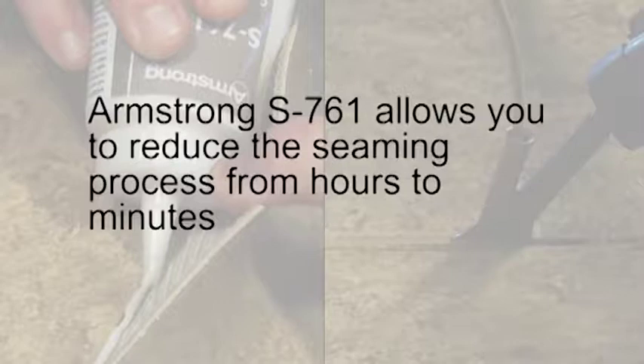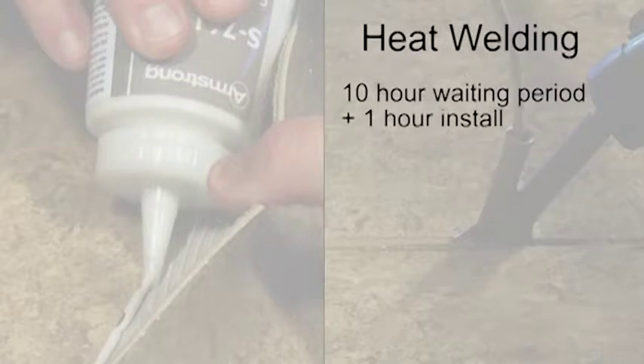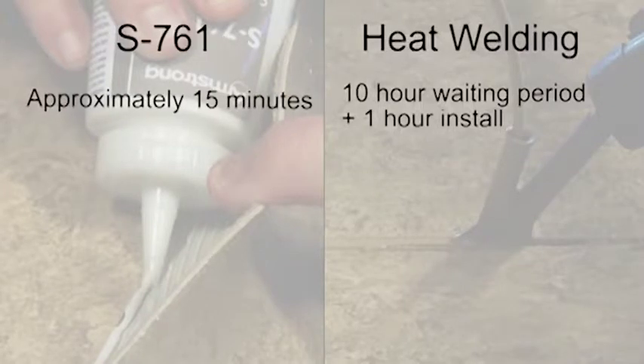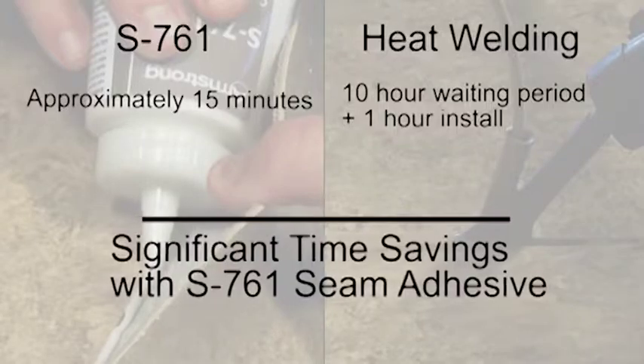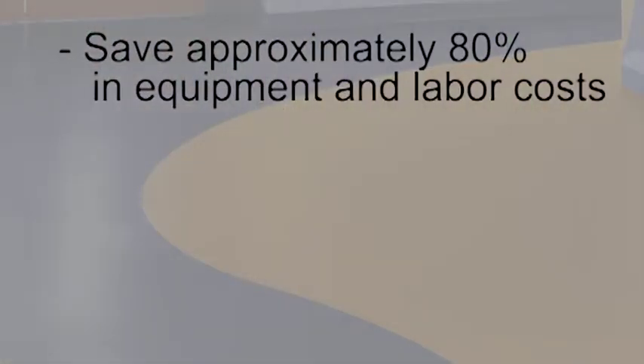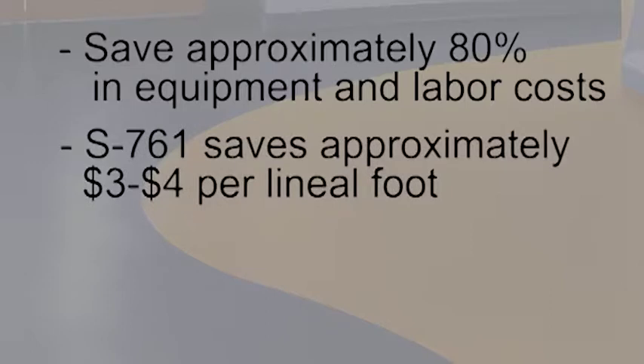Armstrong S-761 Seam Adhesive allows you to reduce the seaming process from hours to minutes. Heat welding requires a 10-hour waiting period for the adhesive to set and approximately 1 additional hour for welding, compared to approximately 15 minutes for S-761, based on 100 lineal feet of seaming. It also allows you to reduce equipment and labor costs by approximately 80%. Compared to other seaming methods, you could save approximately $3 to $4 per lineal foot.